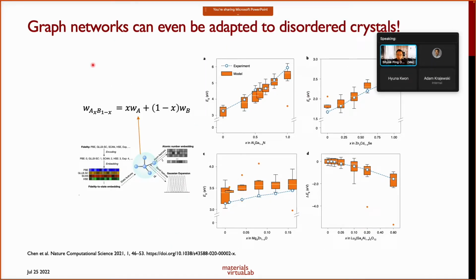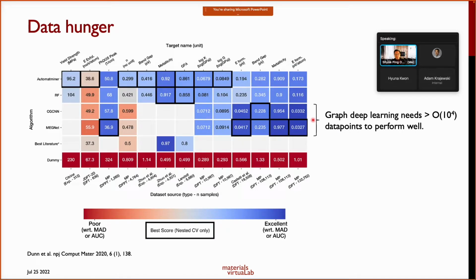Now, we actually even show that graph networks, unlike a lot of the machine learning models out there, can be adapted to disordered crystals. So, for example, if you take the elemental embeddings and treat a disordered site as though it is a linear combination of the embedding vectors of the constituent elements, you can actually use the materials graph network directly and predict the band gaps of solid solution regimes in materials, and the accuracies are still reasonably good, right? And this is not something that you can do with a lot of the machine learning models out there. This is a natural interpolation of the embedding vector for a disordered crystal. Okay. All right.